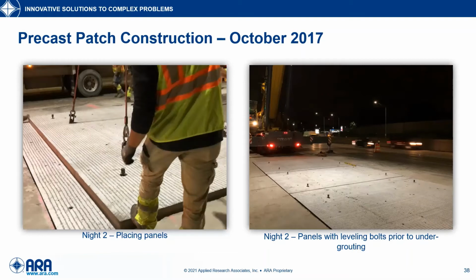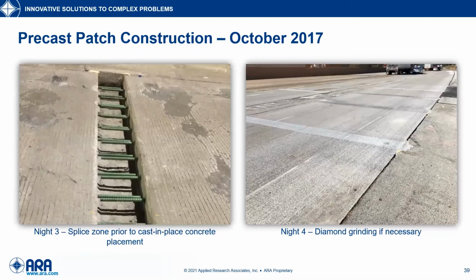The permanent panels were set on leveling bolts and undergrouted, and after the grout achieved strength, the leveling bolts were removed and panels were opened to traffic. On the third night, the temporary panel was removed. That splice zone was backfilled with a rapid set cast-in-place material. For this project, we tried a high early strength UHPC mix and also a steel fiber reinforced CTS rapid set DOT concrete mix design.